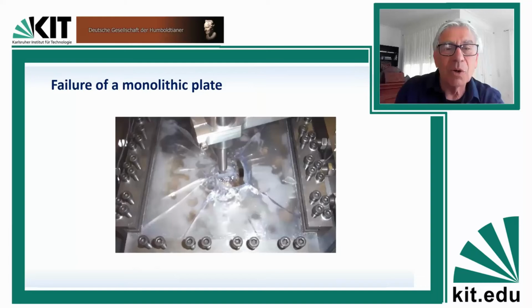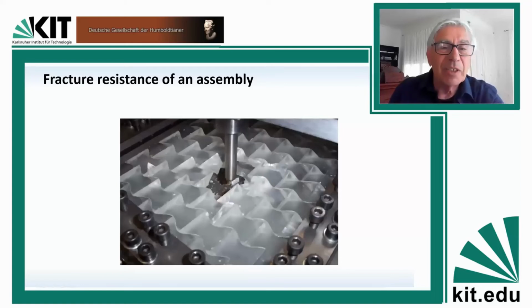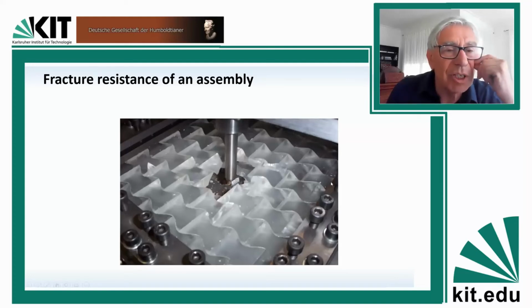They can also resist catastrophic failure, as demonstrated here. Catastrophic failure of a monolithic plate, as opposed to very localized failure of a plate consisting of interlocked blocks. The rest of the structure is actually intact, so that even if you lost some of the elements of the structure, say by projectiles hitting the structure, it still can survive.